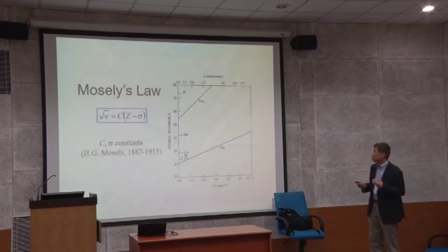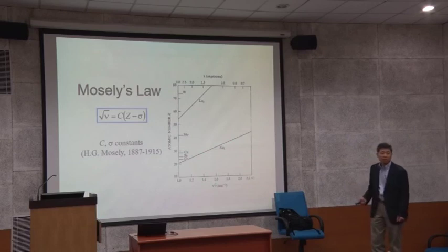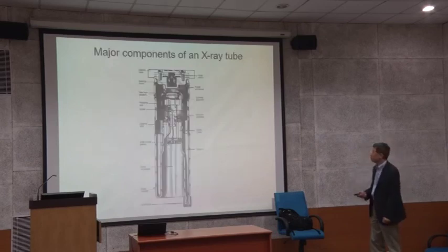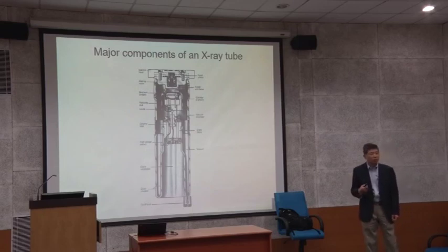Okay. So this one actually tells the wavelengths of X-ray. As you can see, the copper K alpha line wavelength is roughly, for copper K alpha 1, 1.54 angstrom, and then you have different wavelengths for other elements. When you increase the Z number, the wavelengths get smaller because the energy transition is bigger. Okay. So there are many different X-ray sources people use.